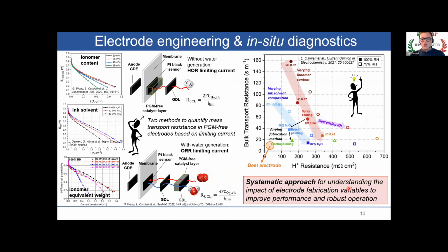Overall, we applied these methods to several different fabrication methods and operating conditions, and we basically provided a systematic approach for understanding the impact of electrode fabrication variables to improve the performance, showing that the best performing electrodes in different operating conditions are the ones that minimize the ohmic proton transport resistance in the electrode and the bulk gas oxygen gas transport resistance.